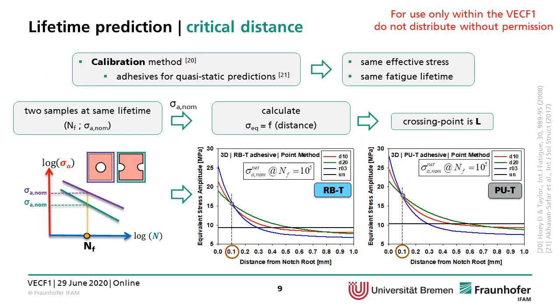Well, one of the main challenges in the use of the TCD for adhesively bonded joints is the determination of the critical distance, so which value of the critical distance to take. In this work, we used a calibration method, which was used for adhesives, for quasi-static predictions. And the idea is that for the same effective stress, you have the same fatigue lifetime.